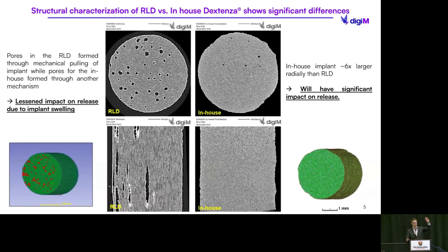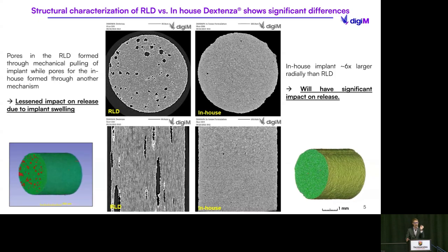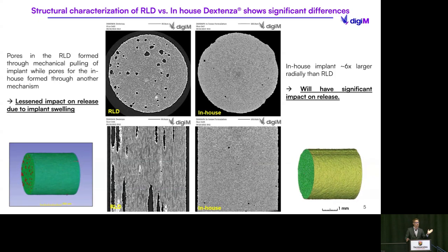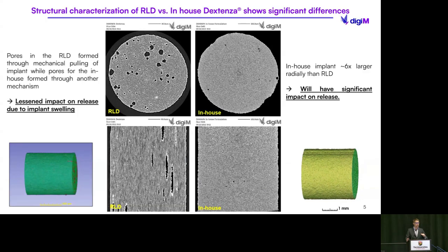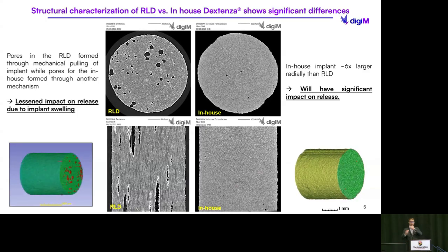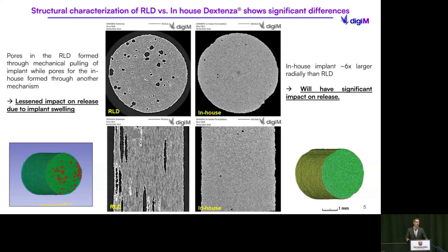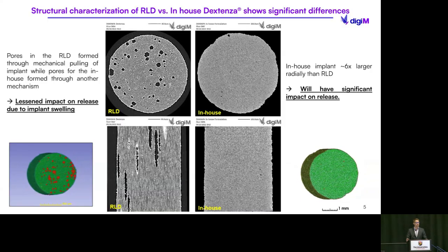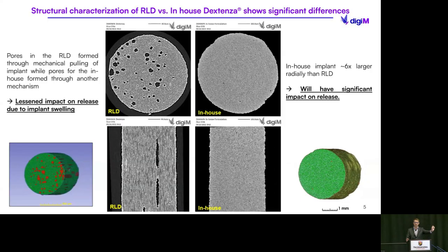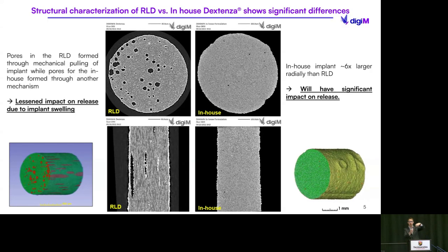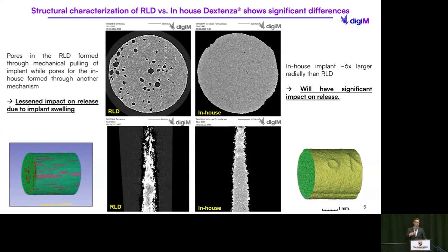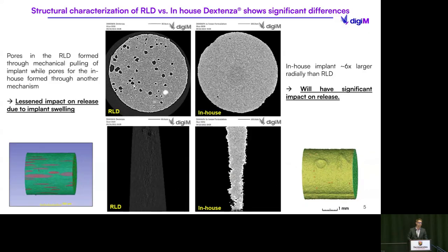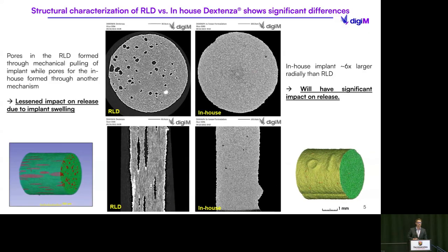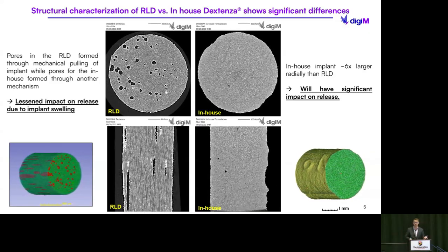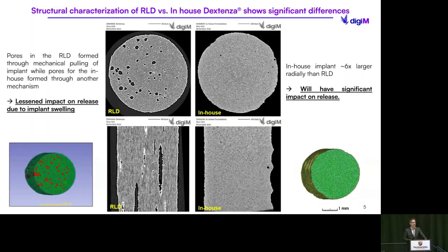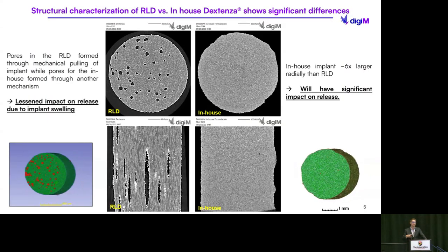If you look on the top row, it shows looking down the main axis of the insert. If you're looking on the bottom row of these movies, what you're looking at is a side view, as if we cut and swept through. And you'll notice that in the case of the RLD, the pores that you see on the top actually are these long scars that exist all the way along the axis of the implant that are not seen in the in-house formulation. So now we have a very interesting scenario.